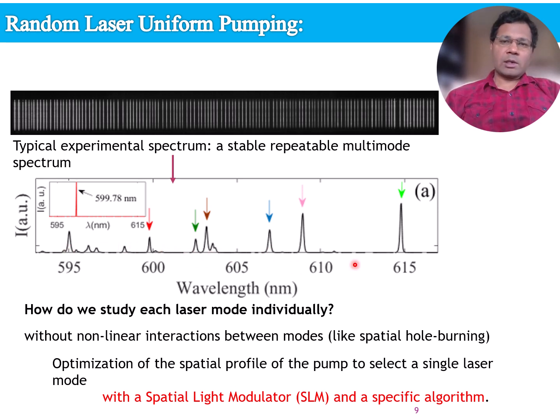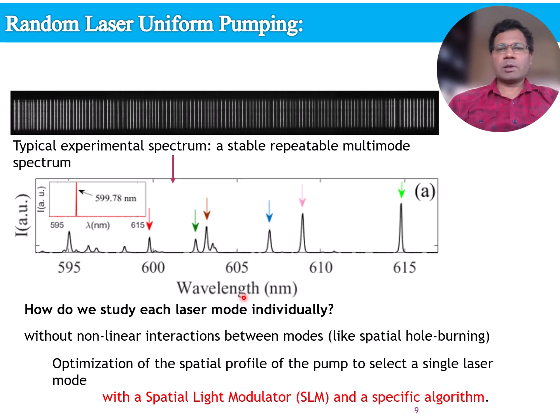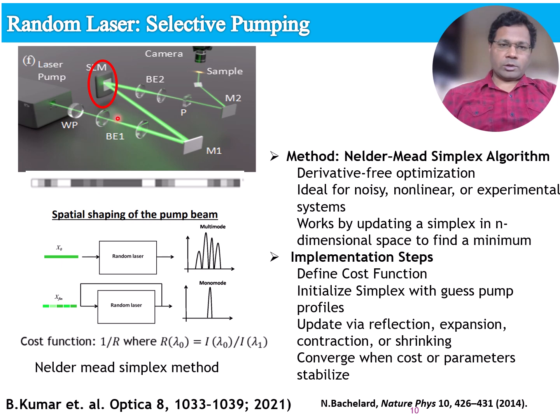But the real challenge is, can a random laser emit monochromatic light like a conventional laser? In the coming slides, I will show we have achieved single mode lasing by applying a feedback based iterative pump optimization method, successfully suppressing the multi-mode emission and achieving single mode operation. To achieve single mode random lasing, we adopt a method where we shape the pump profile to selectively excite a specific mode. This is accomplished by using a spatial light modulator that is controlled by computer generated images to modulate the pump beam before it is projected onto the sample.